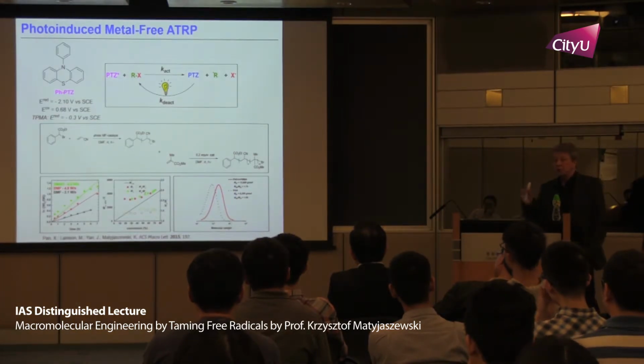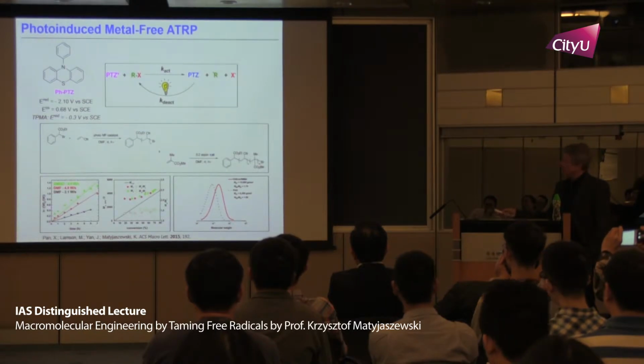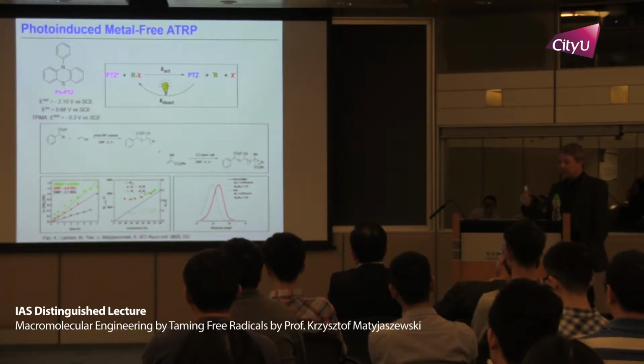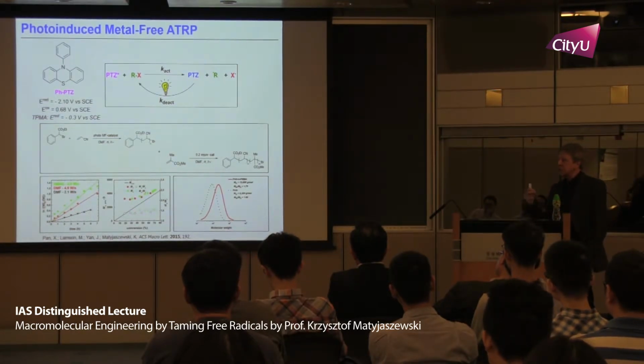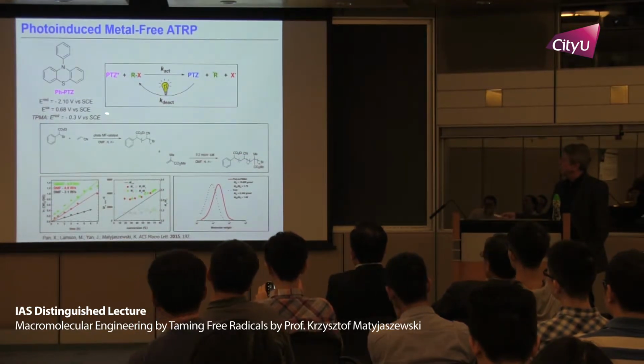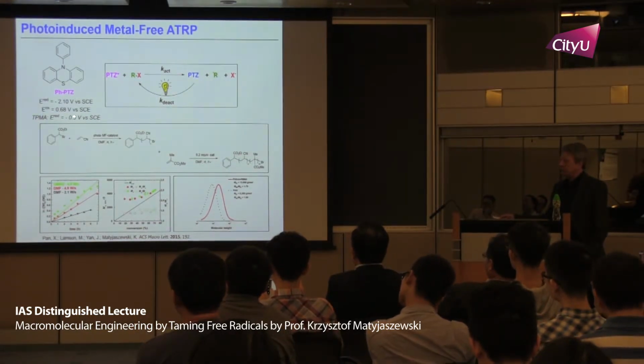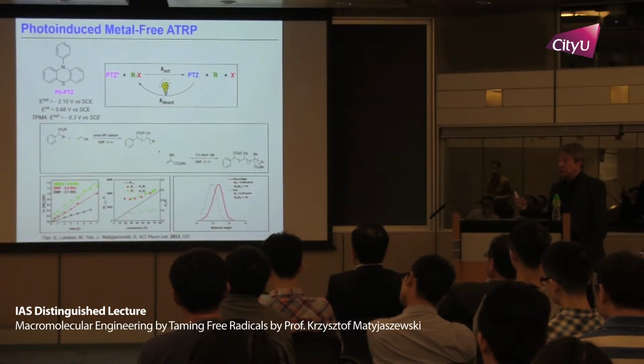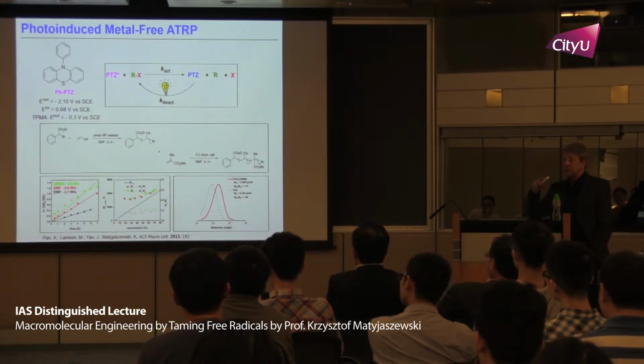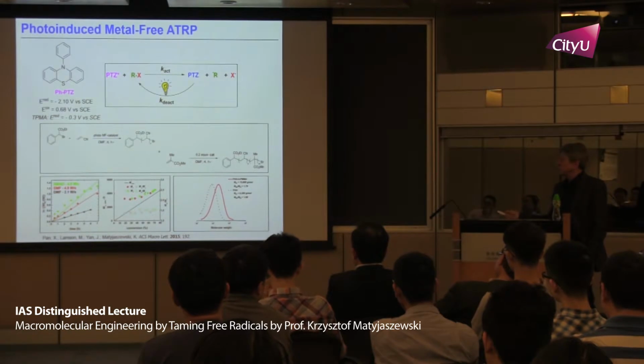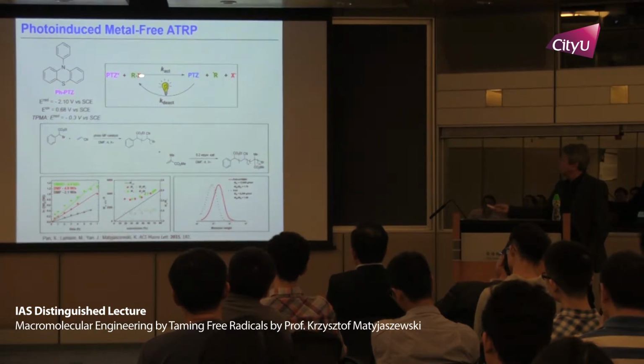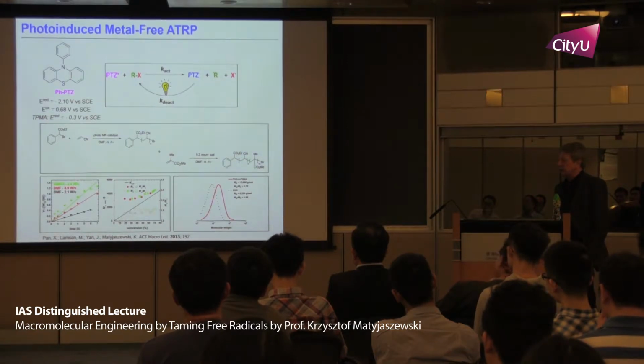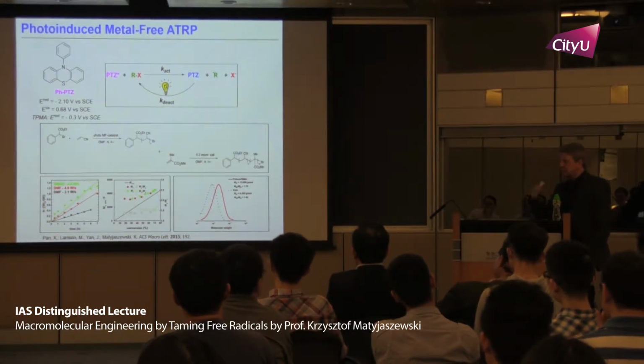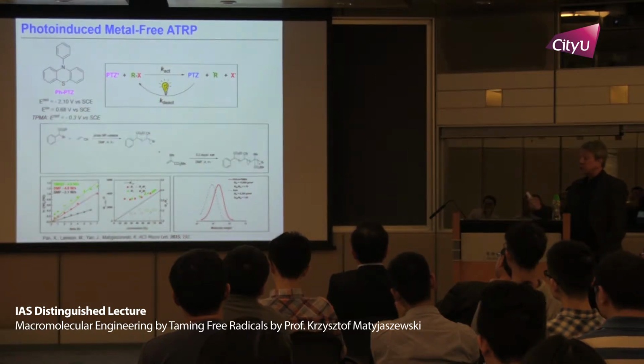So how to do that? You can use also organic photocatalysts. So this is an example of phenothiazine, which can be excited by light to a photoexcited state, which is extremely reducing. So these previous catalysts, they have redox potentials around negative 300 millivolts. This one has negative 2 volts. And you have to realize that 59 millivolts is 1 decade of catalyst activity. So this is like 10 to the power 20 times more reactive. So it gives an electron immediately, and then reduces alkyl halide to radical and the corresponding halide anion. Of course, the lifetime of this species is very short. It is in the range of a picosecond, sometimes femtosecond. So it depends really on the lifetime of this species how you can control this reaction.